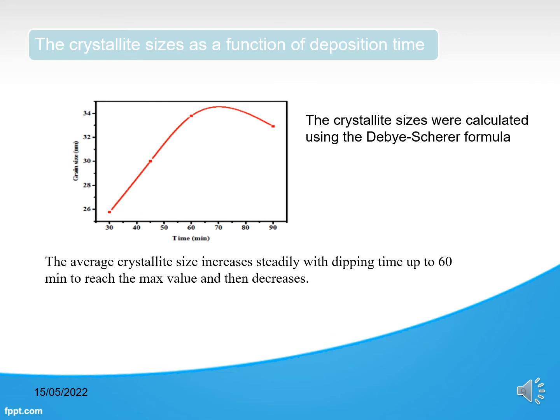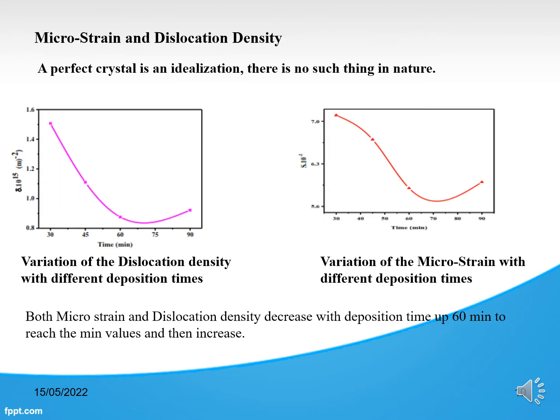The crystal sizes as a function of deposition time. The crystal sizes were calculated using the Debye-Scherrer formula. We see that the average crystallite size increases steadily with the dipping time up to 60 minutes to reach the maximum value and then decreases.